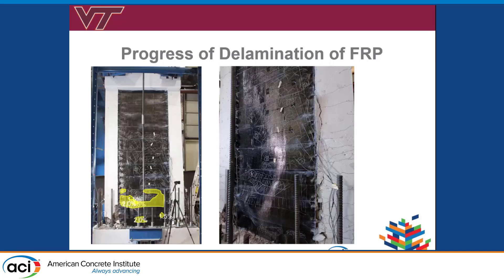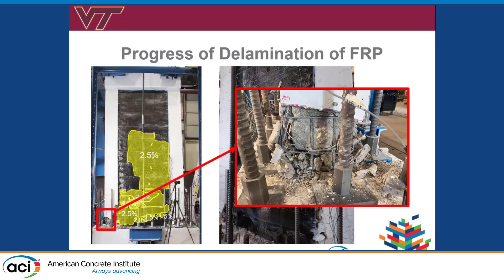At 2% drift we get a little more delamination, but the fiber reinforced polymer is still holding pretty well. The major delamination occurs at our failure drift of 2.5%. The first real mode of failure in this specimen is much more flexural — the column and vertical reinforcement, where we have most of the steel, are experiencing flexural failure modes with yielding. It's ductile, and there's also bar buckling and concrete crushing.